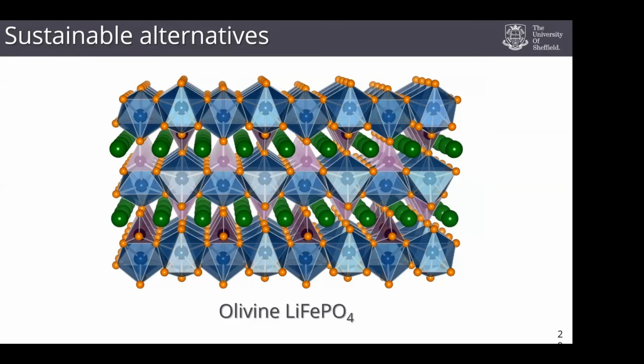Why? Well, if you look at the structure, these lovely blue arrangements here are our iron surrounded by our oxygen atoms. These green spheres are our lithium ions. They sit within these beautiful channels. And then you have these lovely tetrahedra. These are our phosphate groups, which sort of bridge the iron atoms and add some structural stability to this whole thing. So it looks wonderful. All those lithium ions can move in, move out of that spot quite nicely.